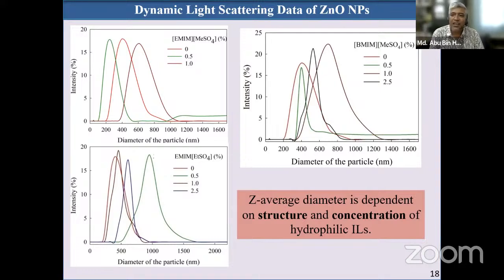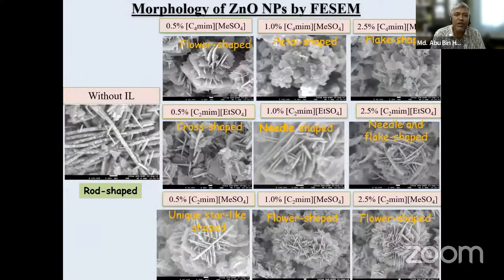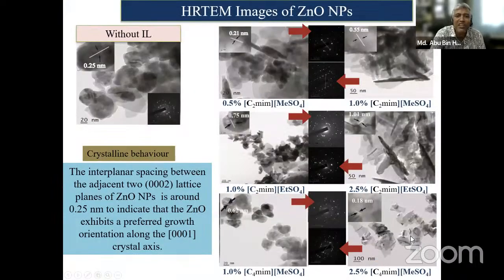To check the real diameter, we had to carry out some electron microscopic measurements, and naturally we carried out FESEM studies without ionic liquid as well as with ionic liquids of different kinds at different concentrations. You can see that the structure varied from flower shaped, petal shaped, to flake shaped. This is dependent on concentration, and also depending on the type of the ionic liquid, the shape changed to cross, needle and flake. Here star-like, here you can see like a flower, and this is a beautiful flower. So the morphology was very widely varied and controllable.